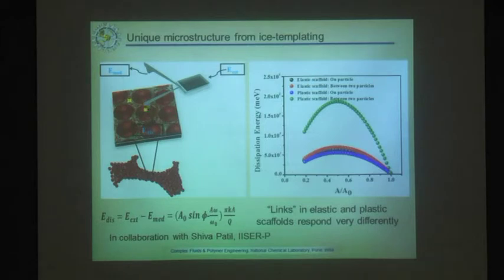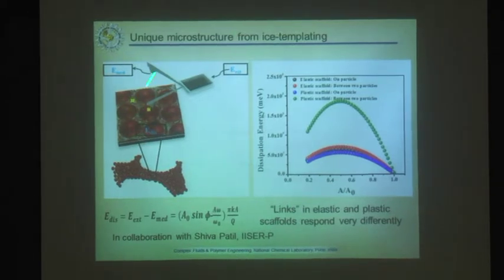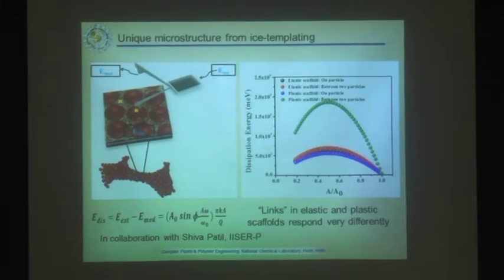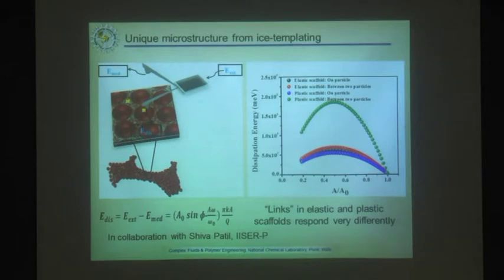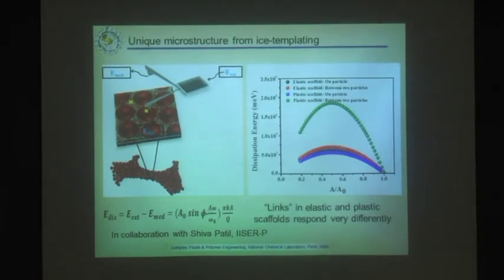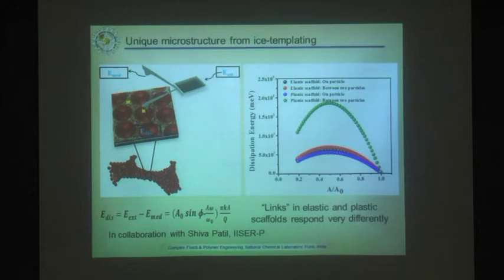We take a point on the sphere, which is still covered with the organic, and we get some dissipation. This dissipation doesn't really change in the samples which recover elastically if you go to a point between these spheres. But when you do the same thing for the material which is cross-linked in the absence of ice, you see a much larger dissipation. So I think these are really the first clues we have that there's some difference in the spatial chemistry in these materials. What the molecular origin of this is, is not clear to us at this time.